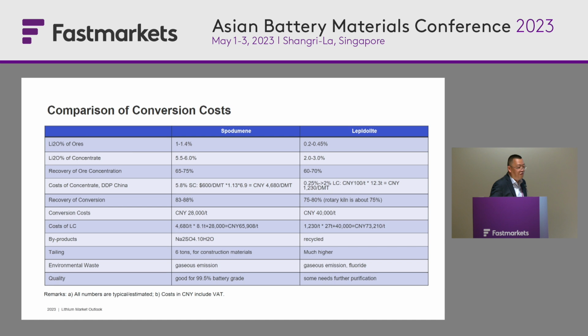I mean, okay, so that's the estimate of cost for lithium carbonate, and you have different byproducts. In the lepidolite conversion, the sodium sulfate can be recycled for use, okay? And also you have a totally different composition of tailings. For spodumene, you have 1 ton of battery grade carbonate, 2 tons of sodium sulfate, and 6 tons of tailings, which are typically sold to the construction material market.